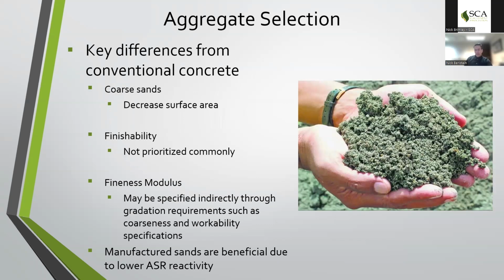A few, but much less requirement in the sand. The biggest consistency issue we generally see with sand is moisture. However, prior and during mix design stages, but prior to production, it's often about making sure we're not going to have any sort of reactivity with the sand. ASR testing is very common in most of the regions we operate, so it makes it a bit easier to make those supply decisions early on, but ensuring that we don't have any sort of failures or we're not going to have any reactivity is always a key effort in our initial mix design and supply sourcing issues.